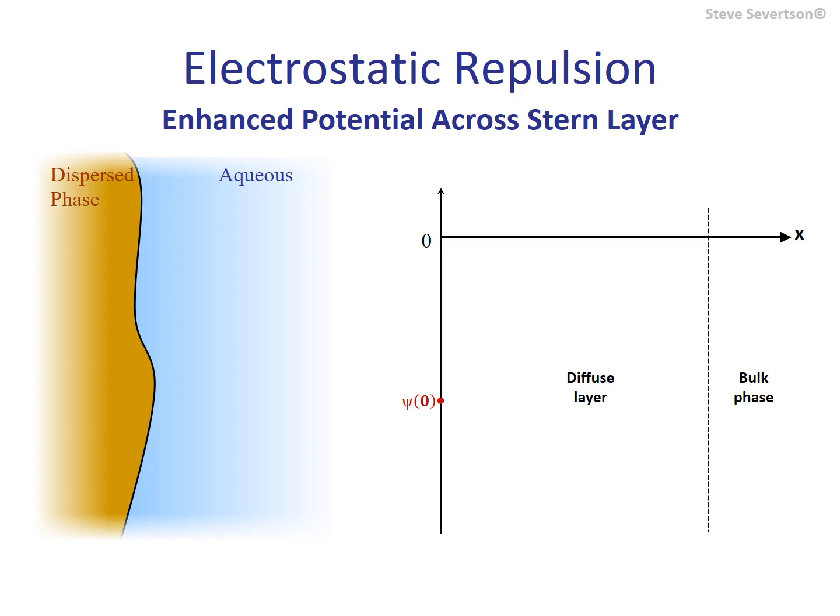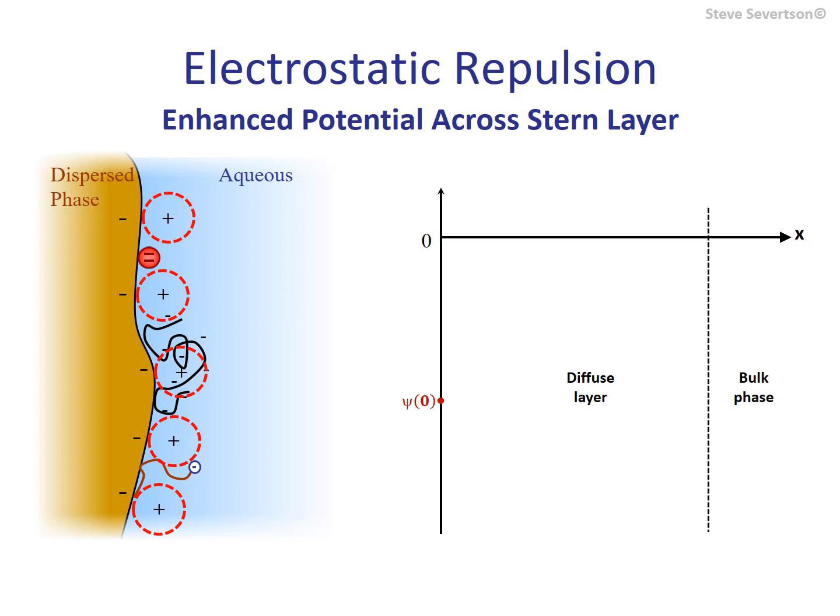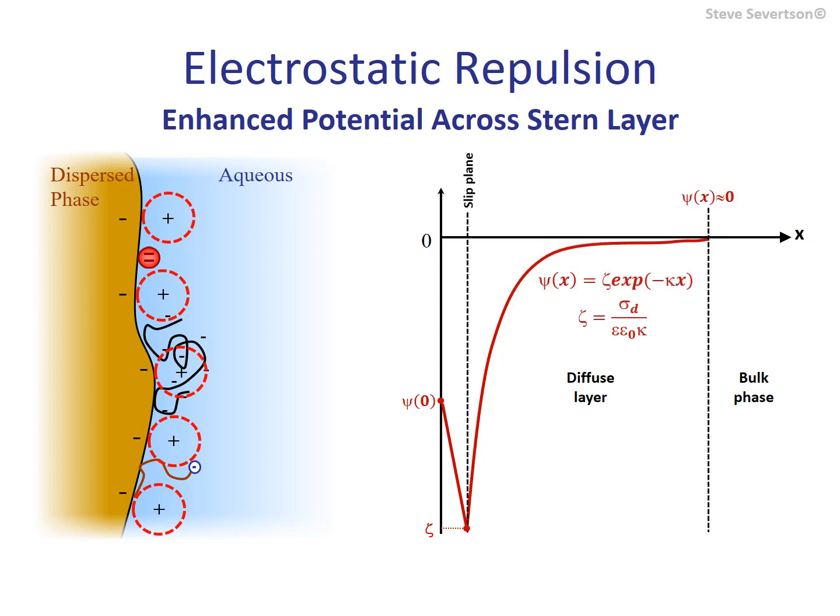In addition to hydrated ions, which form the Stern layer, a surface placed in water will attract other solutes. And in the case of surfaces possessing relatively low charge densities and surface potentials, other adsorption mechanisms are often at work, in particular those resulting from solutes being pushed out of the aqueous phase. This can include anionic surfactants and polymers and even multivalent coions. Their adsorption builds charge in the Stern layer, increasing the magnitude of the Stern plane potential, which is assumed to be about equal to the zeta potential. As discussed, the charge density measured from this perspective includes such components and thus provides a clearer picture on the influence of stabilizing additives.